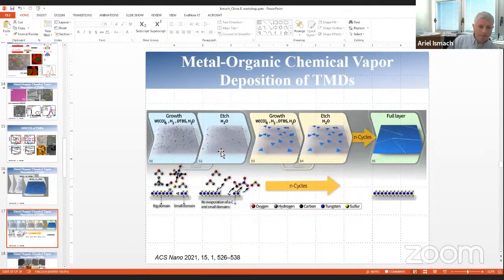Now, when you implement this growth and etch pulses, we grow the layer, we start the same growth as I showed you before, and then we stop the growth and we etch with very small amounts of, in this case, water vapors. So we evaporate not only the carbon impurities, but also the small and defective domains that were grown in the beginning. Therefore, we not only clean the surface from carbon impurities, but we allow the higher quality domains to continue the growth. And we end up with highly crystalline domains and highly crystalline films.